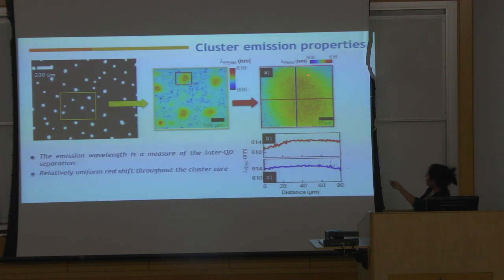If it's very uniform, and we took some line cuts here, you can see the color is very uniform inside a cluster. That means that the cartoon that we have of the quantum dots sitting at almost equal distances throughout this big giant cluster is good. So although the liquid crystal is assembling them into aggregates, it's not true aggregation. There is some sort of short-range order in the aggregates. So we've organized them in a nice layer, if you want, in 3 dimensions, of course, but there is some sort of ordering in the system.